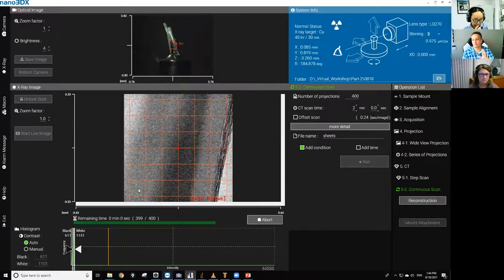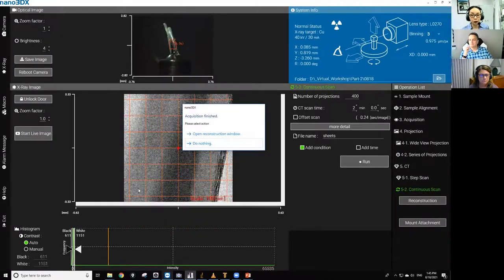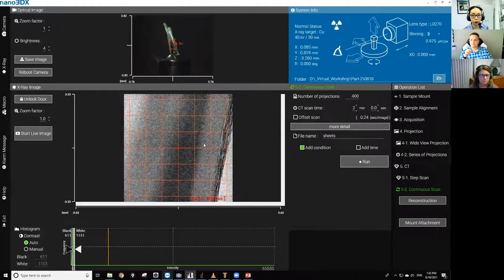And so is there any benefit to making those modifications? In that case, the benefit is that you can reduce the scan time. Because 4x4 means that you're combining more pixels together, that usually means a higher X-ray count, and a higher X-ray count means that you can shorten the exposure time or scan time. What you're losing there is the field of view. When you change the lens to do that, your field of view becomes smaller. But if your sample is tiny, and by changing the lens you still cover the entire sample and go from 2x2 to 4x4, you can do a scan faster. So the speed is the benefit.